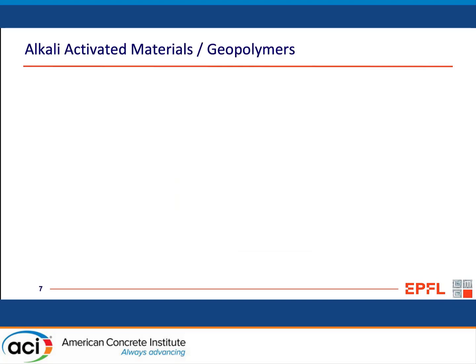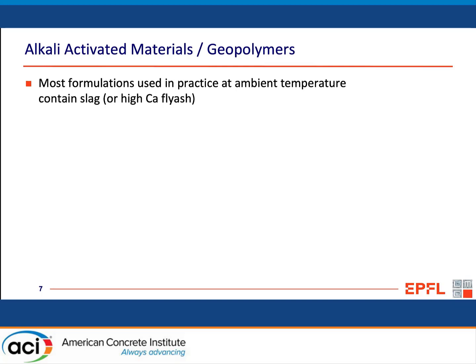So let's come back and look at these alkali activated materials. Well, if you really look into the few demonstrations that have been done around the world, you will see that all these formulations used in practice, which can be made at ambient temperature without heat curing, contain slag or high calcium fly ash. So fine, you can have a few niche applications. You can use that unused amount of slag and some fly ash, but that's going to have a pretty piffling impact on world CO2. It's not going to get us out of the mess we're in.